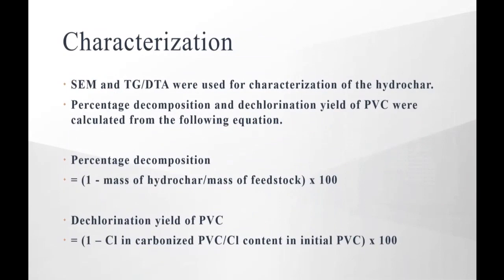We measured the mass of hydrochar and chlorine content in PVC and then calculated the value of percentage decomposition and dechlorination yield. After the carbonization, we can separate the carbonized biomass and PVC. Therefore, the dechlorination yield was obtained from the chlorine content in carbonized PVC.